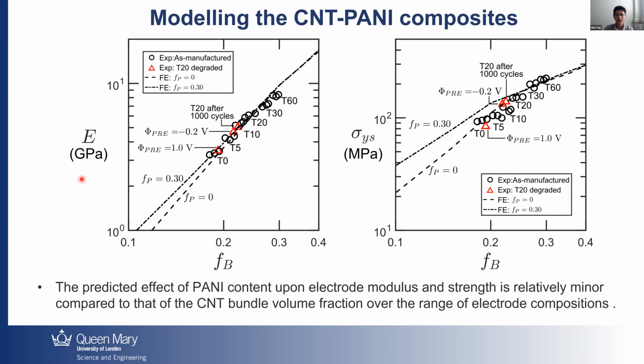For example, you see the predicted effect of the PANI content if we increase the PANI. It's relatively minor compared to that of the CNT volume fraction, FB. So if we change the CNT bundle fractions from here to here, there's a significant change of the modulus and also the yield strength. But if we change the PANI volume fraction from 0 to 0.3, there's a limited change on that.